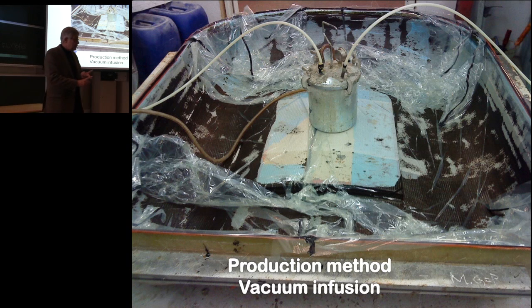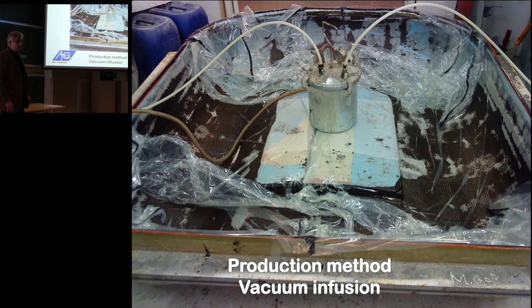because the solvent in the resin was water, and natural fiber contains water, and it would cure at 138 degrees. What happens with water around 100? Not nice at all, right? It starts to boil. So we needed to reduce the water content, leaving just enough water for the polymerization chemistry. So we tested how much pre-drying we should do, at what temperature and for how long. Roughly, not to be perfect, roughly 6 hours at 60 degrees in an oven for pre-drying. And when we had this stabilized, we turned it up to 138 degrees for 10 minutes and it was done.